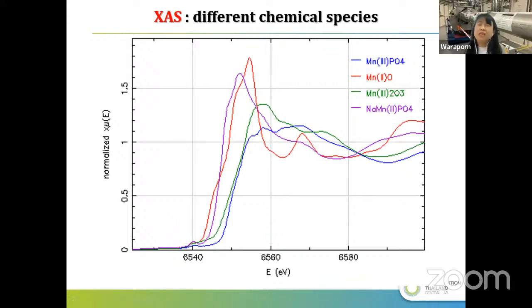As I mentioned, the oxidation state of a sample can be distinguished by X-ray absorption spectroscopy. Like for this one, if you would like to probe manganese, this is manganese 3 phosphate. Here is the spectrum. The spectrum is shifted to higher energy, but for manganese 2 oxide, the energy needed to excite is lower. So if your sample has different oxidation states, the spectrum will be totally different, and also the shape of the spectrum is different. You can use the shape at the tail of the peak of the spectrum to measure EXAFS as well, to see the bond range and the neighboring atoms.